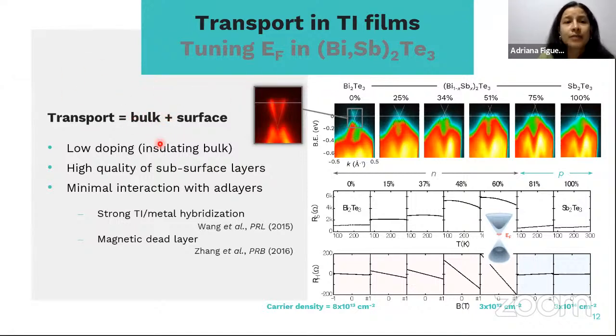In these materials, we have a combination, as I said, of bulk transport and the surface states. But in an ideal TI, we want to make sure that the one that contributes the most to the electronic transport is the surface states, so that we can use them for different applications, in particular for spintronic applications. And we've seen that in this alloy we were able to get such conditions around 60% of antimony, right?